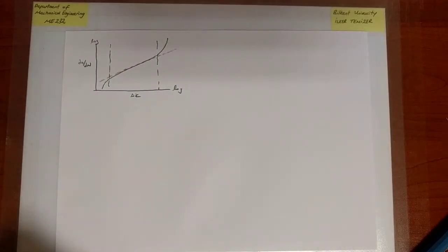So what is special about the high regime? Notice that here we're going towards fracture. When does fracture occur? It occurs when the stress intensity factor is equal to the fracture toughness of the material, right? Now, the stress intensity range cycles from the minimum value to the maximum value. The critical stress intensity value is the maximum value. So here, ultimately what is happening is that Kmax is going towards the fracture toughness.